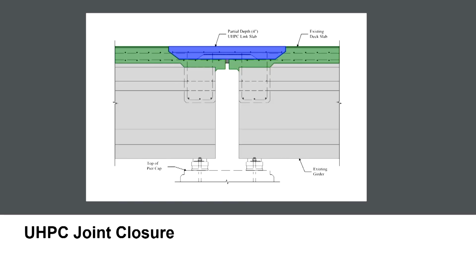We'll also use UHPC for the joint closures that we're doing. Many of the joints on the bridge have been closed, or the eligible ones at this time, in the previous rehabilitation, but there's a couple that we can add to. The main benefit that we're looking at for these UHPC link slabs is that you get to have a partial depth demolition, which increases the construction speed, so you don't have to demolish quite as much material, and you also get the benefit of some built-in formwork from the existing deck already being there. I understand we're going to learn a bit more about UHPC link slabs tomorrow, so I'll leave it there on this one.